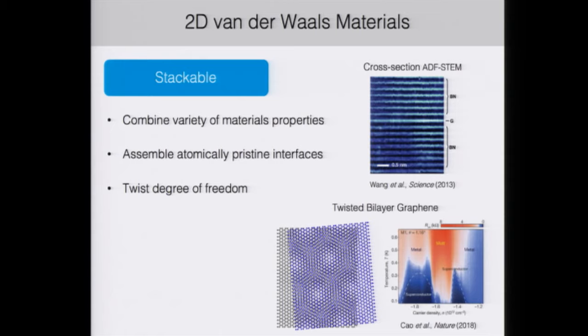And more recently, there's been a lot of attention on the twist degree of freedom. If you have epitaxial growth, you don't have the flexibility to twist the layers with respect to one another, but van der Waals materials offer this tuning parameter. Our group demonstrated last year that if you take 2 layers of graphene and place them at the magic angle of 1.1 degrees, you can access this beautiful phase diagram by applying gate voltages and access superconductivity, Mott insulating states, and even ferromagnetism. So there's a lot of room for exploration now that we have this additional degree of freedom in these systems.